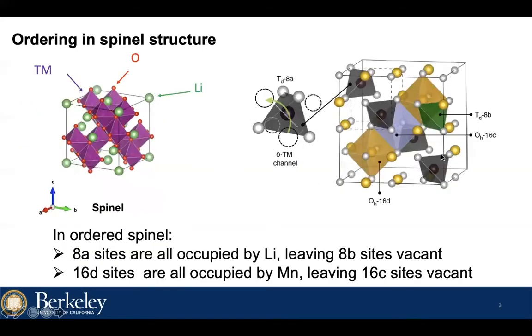To do so, spinel is a very interesting and promising structure. Instead of cobalt, manganese is used in the spinel compound, which is much cheaper than cobalt. Here is a spinel structure. You can see the 16d site is all occupied by the manganese, and they face-share with the vacant tetrahedral site, which is the 8b site.